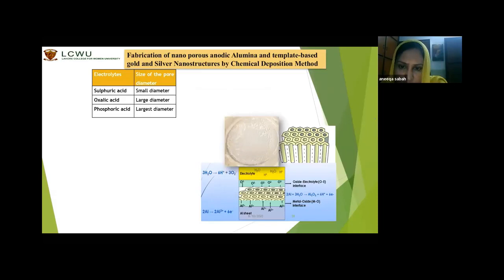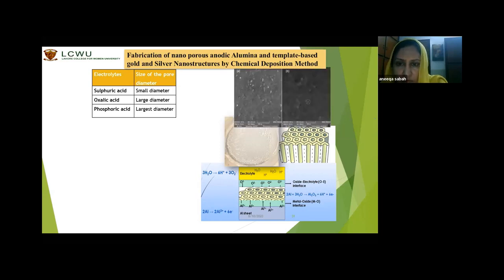This was the kind of membrane we got for alumina, and the template was observed under field emission scanning electron microscope, and pores are there. We were able to get the porous structure.